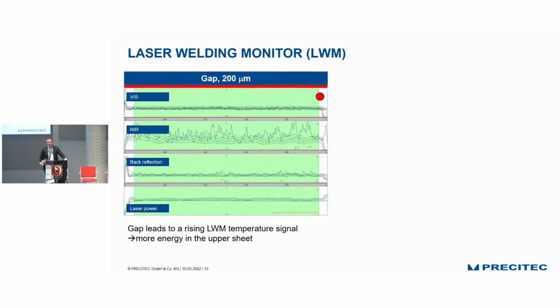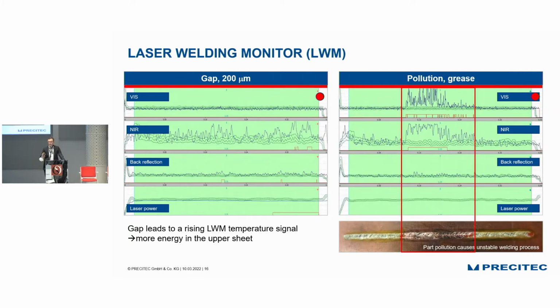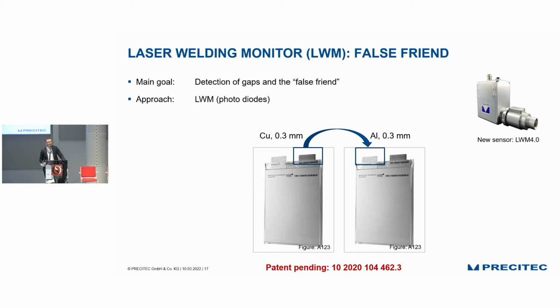The next intentionally applied defect is a gap. If you have a gap between two sheets, the temperature just cannot flow fast enough from the upper to the lower sheet, and there's a tendency that temperature increases on the upper sheet. We can see this temperature increase by an increase of the photodiode signal which is sensitive in the near-infrared wavelengths. This is how we detect gaps. And finally, pollution. If you weld over, in this case, intentionally applied contamination, you get a burning event, and this burning event is emitting light in the visible range.